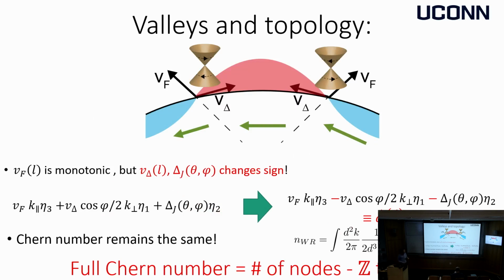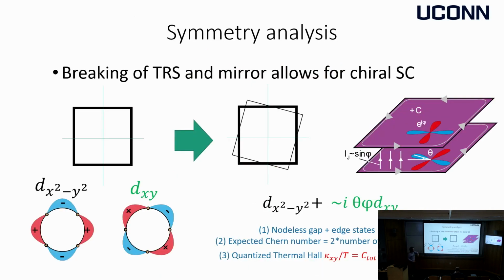One thing I want to mention is that I've been treating so far just one pair of Dirac cones, but I have a whole Fermi surface, and if you remember, there are actually four pairs of those Dirac cones, each doing its own thing. In the interest of time, I'm just going to say the result. If you analyze what happens to every single Dirac cone on the Fermi surface, you will find that its contribution to the total Chern number, the integrated Berry curvature, is the same. So you are actually getting a topological superconductor. You expect a gapped bulk and a gapless boundary, and if you introduce vortices, you also expect zero energy modes in the cores of these vortices. This happens at any twist angle, any phase difference.